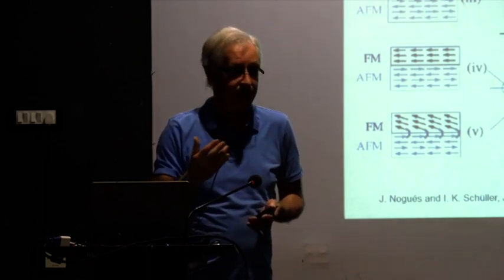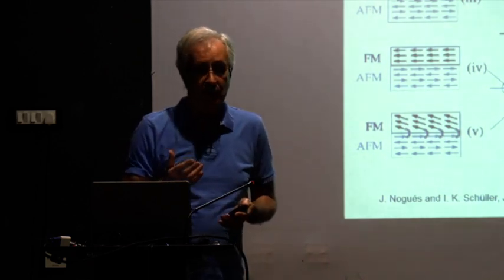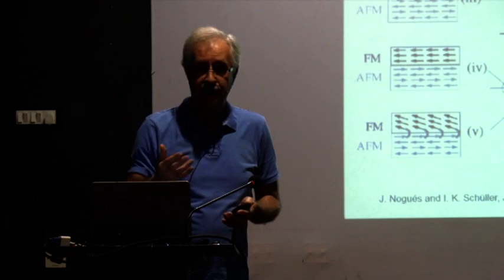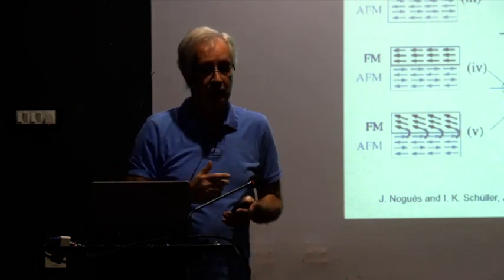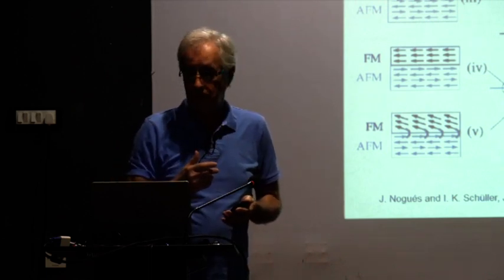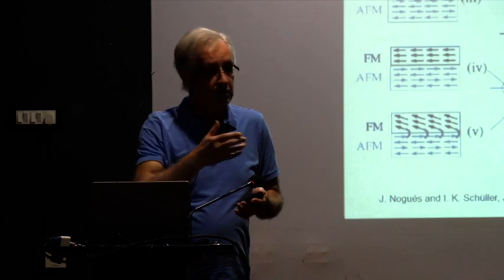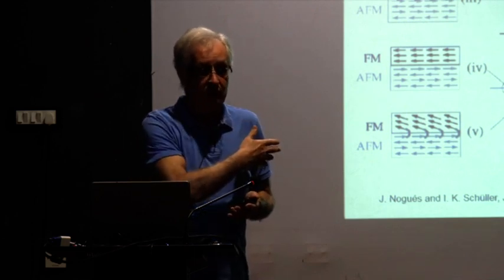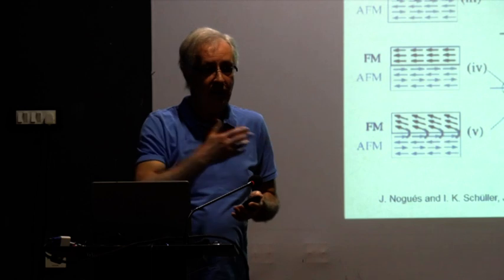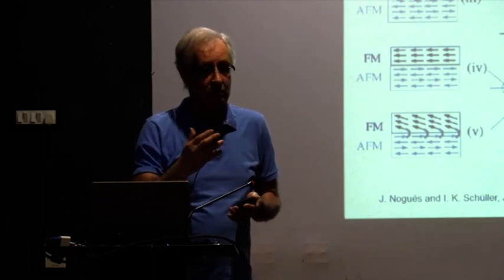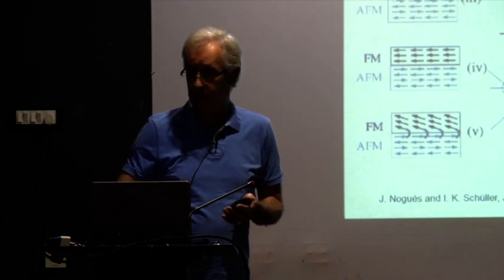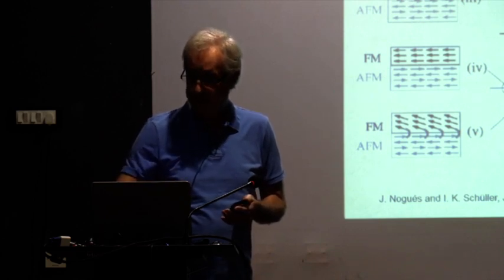Okay? It's important in this sense that when you're measuring complex systems, you've measured the magnetization and so on, and then you go down to low temperature, and then you cool it in a field, and you measure something, and if you see shifted curves, then you can be sure that you have some kind of an antiferromagnetism in there.